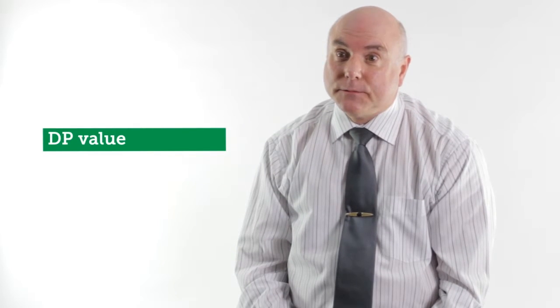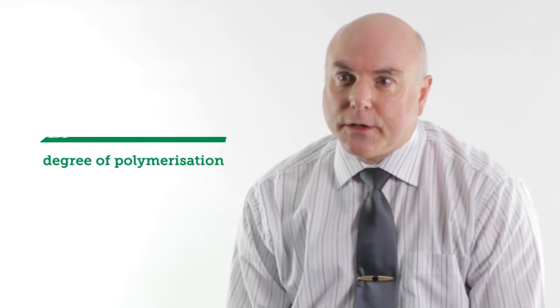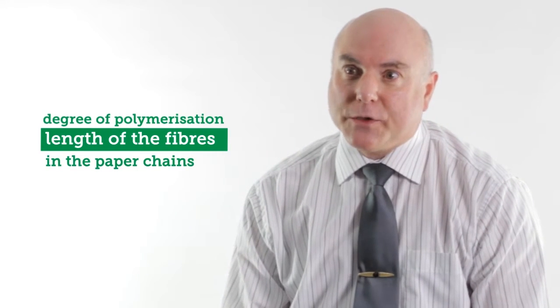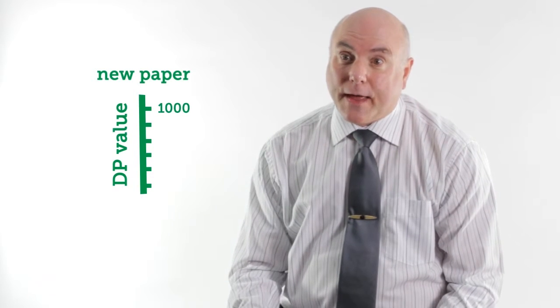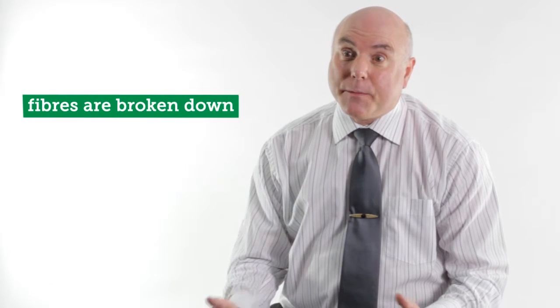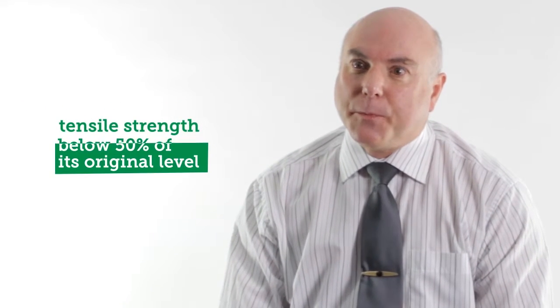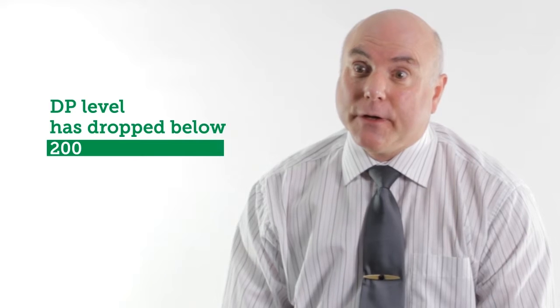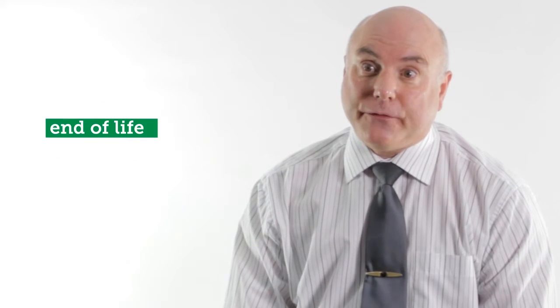The end of life of paper could be determined by looking either at the tensile strength or the DP value. The DP, or degree of polymerization, represents the length of the fibres in the paper chains. The higher the number, the longer the fibres and the stronger the paper. New paper has a DP value of around 1000, and as it ages, its fibres are broken down. They become shorter and the paper loses its tensile strength. When the tensile strength has dropped below 50% of its original level and the DP level has dropped below 200, the paper can be said to have reached end of life.